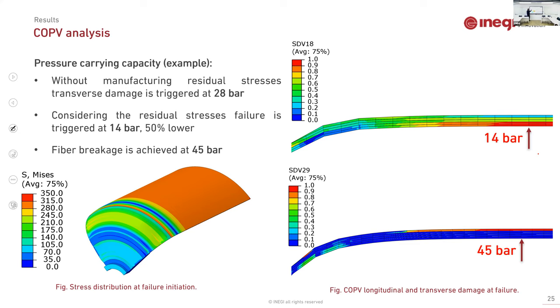Without considering the residual stresses from manufacturing, the pressure needed to activate the transverse damage is 28 bars. Okay. But if we consider the residual stress state that we get from the previous slide, the internal pressure to activate the transverse damage in the internal layer is 14 bars. The load carrying capacity is reduced to half. This does not mean that the vessel will fail. It only means that a crack will appear and maybe a leakage could happen. In any case, the fiber failure is reached at 45 bars. Okay? Depending on the fluid and the material, a leakage will develop there.